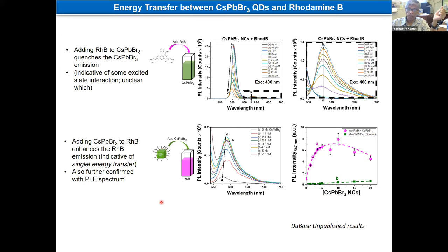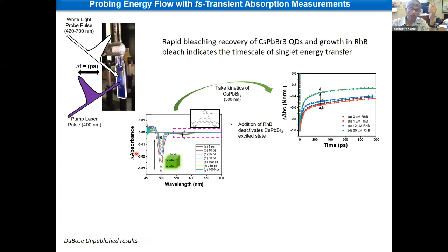We also probed how fast the energy transfer is occurring by doing transient absorption measurements. And you can see here, this is the excitonic bleach of cesium lead bromide. And as this one decreases, we see an increase, a bleach of rhodamine B. And that is because you are forming the singlet excited state. So we can follow the decay recovery of this cesium lead bromide. And when you put the dye, it becomes faster. Note that fast component here.